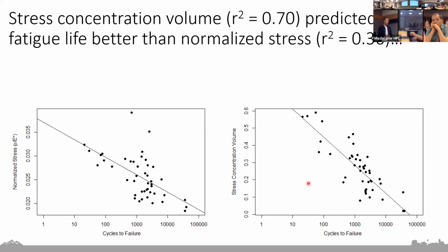So getting into some of the results, we found stress concentration volume was a much better predictor of fatigue life than normalized stress. And for normalized stress, we divided our stress by the initial modulus. So we weren't directly measuring strain, but for all intents and purposes, this is a measure of strain. So we again see stress concentration volume at a much higher correlation.